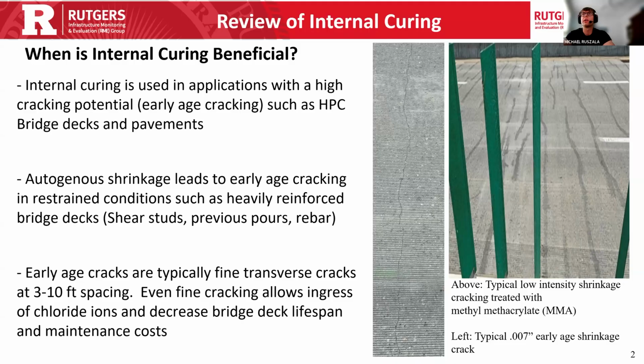You can see on the screen a typical cracking pattern. This is due to bridge decks typically having a high concentration of rebar, adjacent previous pours, shear studs, and all of these things at early ages before the concrete has developed proper strength, and it experiences this high degree of autogenous shrinkage. It develops these stresses and results in this distinctive cracking pattern.